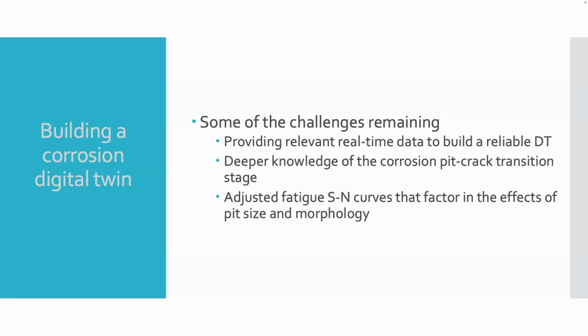Is accurate. Deeper knowledge of the corrosion pit to crack transition stage, because we know that the corrosion pits on the surface act as crack initiation points that can lead to failures. And based on that, we can make adjusted fatigue S-N curves that factor in the effects of the pit size and their morphology. Am I okay with time?